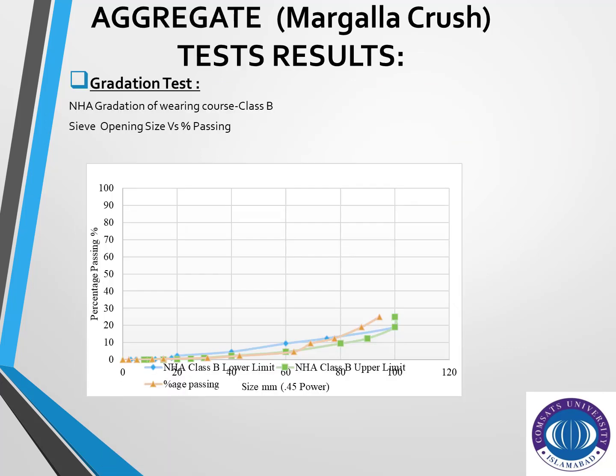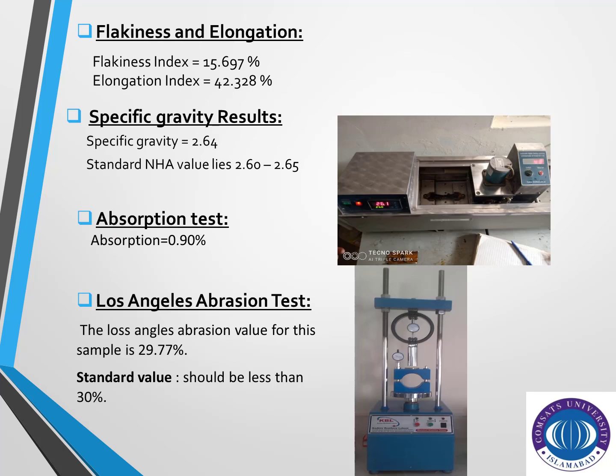Here are some test results we mention in this slide, shown through a graph of opening size versus percent passing. It shows variation by different sizes and passing in different percentages. Here are the values of flakiness and elongation. Flakiness index is 15.6% and elongation index is 42.3% for the material that we use. For specific gravity we get 2.64, and the standard value lies between 2.60 to 2.65. The absorption test value is 0.9%.